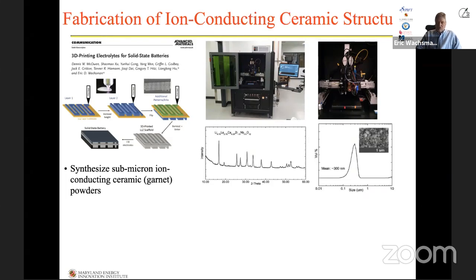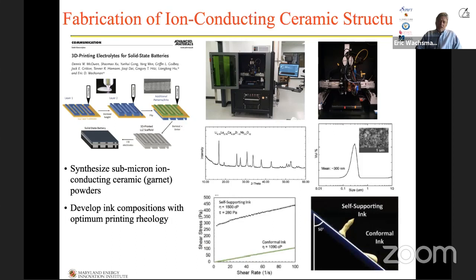So they're on the hundreds of nanometer scale range that allows them to flow through the capillary on the 3D printer. You've got to develop the ink compositions with the optimum printing rheology. And so you see the shear stress versus shear rate on the left, and then sort of an example of what that does. So those are two different prints, and they're held at a 50-degree angle.